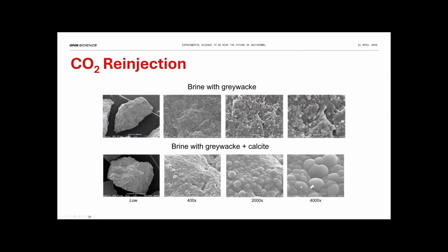So what's happening is the reinjection brine, which is at pH 4.5, is going into the formation, and if there's calcite in the formation, that calcite reacts very rapidly. And what it does is it neutralizes the brine, and the pH of the brine will actually go up to 7.8 or even 8. And as soon as that happens, of course, all your acid inhibition of silica polymerization and scaling is gone, and you're actually precipitating out dramatically a large quantity of silica quite rapidly because of the high pH.